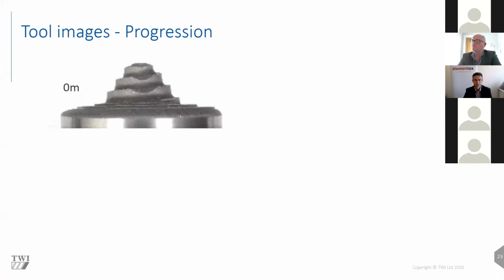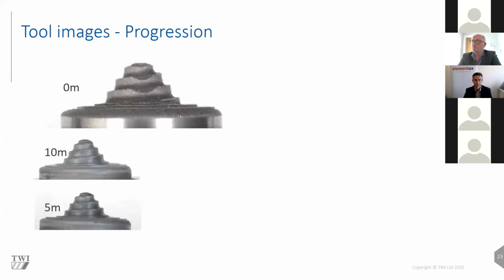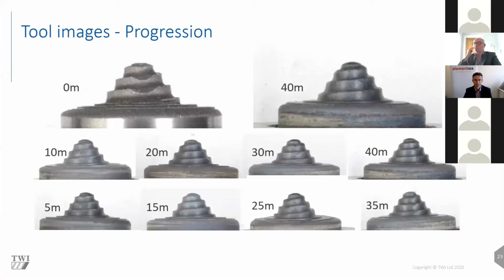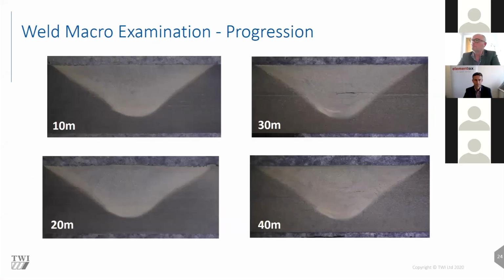The next slide, if Nick builds it up, will show us what the tools look like during the different stages of welding. And so between 0 and 40 meters of welding, the amount of wear that accumulated on those tools was negligible. And so the tools were still capable of giving a good, consistent weld. A quick look at the weld sections. These are sections through the welds taken at the 10, 20, 30, and 40 meter marks. And in every case, we've got a fully consolidated weld with no internal defects. So again, that shows that the tools were offering a very consistent behavior.